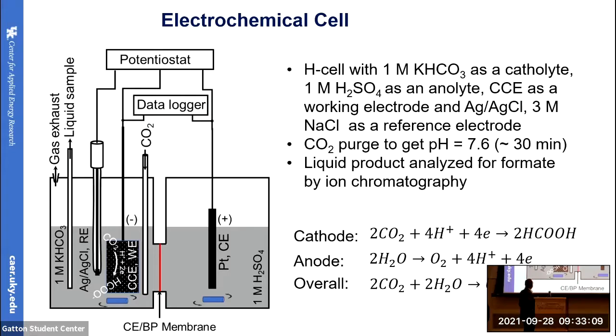This is our reference electrode, silver chloride, and the carbon dioxide is purged into 1 molar potassium bicarbonate solution to get a pH of 7.6. And here we have a data logger for measuring the cell potential during the reduction process.